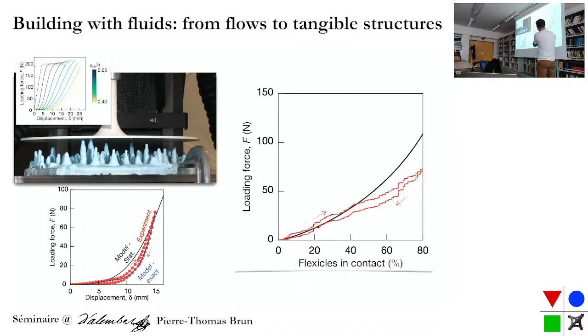The force is actually increasing for 2 reasons, right? You have these bumps, these fingers, and you're compressing them. If you think about them as being elastica, actually they're sort of compressible elastica, so you compress them a little bit, and then they buckle. So it makes sense that you will increase the force initially. But the other thing that happens is that they don't have the same size, and so as you indent, you're making contact with more and more of those posts, right?